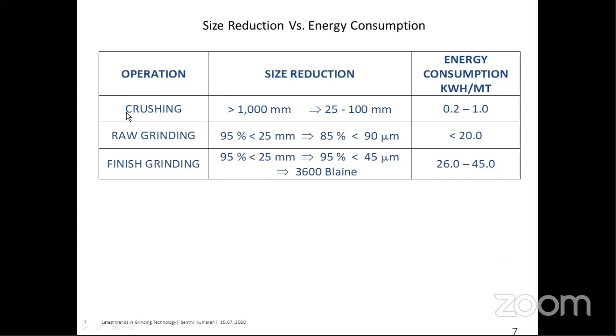When we look at crushing, the size reduction is from above 1 meter of rock down to 25 to 100 mm, but the power consumption is only 0.2 to 1 kilowatt hour per metric ton. For the raw grinding, the 25 mm particle is reduced until 85% is less than 90 micron. The energy consumption is less than 20 kilowatt hour per metric ton. In the finish grinding, the same 25 mm clinker is reduced until 95% is less than 45 micron, where the power consumption is 26 to 45 kilowatt hour per metric ton.